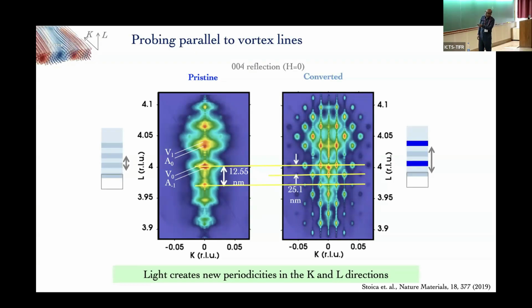I'll show you a few cuts. So this spacing is 12.5 nanometers. That's the lead titanate, strontium titanate, lead titanate, strontium titanate. But after you hit it, you see there are these half order peaks here, which means half in reciprocal space means double in real space. So 12.5, this is 25. Right? So there's something about this where this is lead titanate, strontium titanate. The second lead titanate is not the same as the first one. And then you have to go to this one to get the same thing as that. So it's doubled the unit cell in the vertical direction, right? Something light has done to double it, okay.